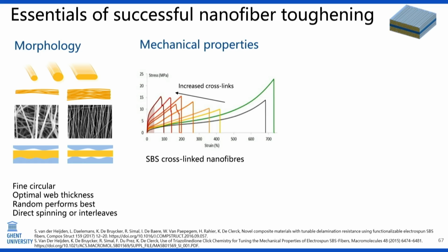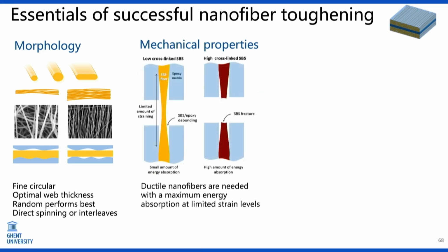First of all, you need fibers with a high energy absorption during yielding. But if you do this at very high strain levels, then of course we have a very big crack, which is unwanted. So we need the optimal ductile nanofibers with maximum energy absorption at limited strain levels. Otherwise, you just open up the crack and they don't do anything.